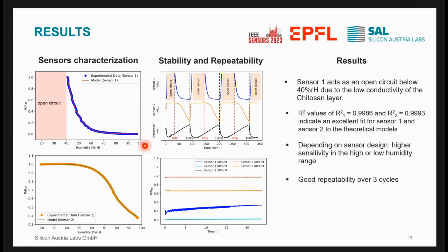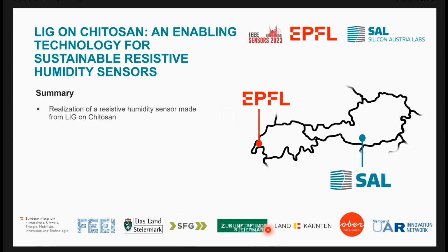And the sensors have demonstrated good repeatability over 3 cycles, as shown in this upper right graph. Also, the sensors have been shown to be stable over a period of 24 hours, as seen here on the lower right. So to summarize, we've demonstrated the realization of a resistive humidity sensor made from LIG on chitosan, which poses a more sustainable approach to resistive humidity sensing by employing bio-based materials and sustainable manufacturing. By using different designs, you can obtain tunable sensor characteristics.